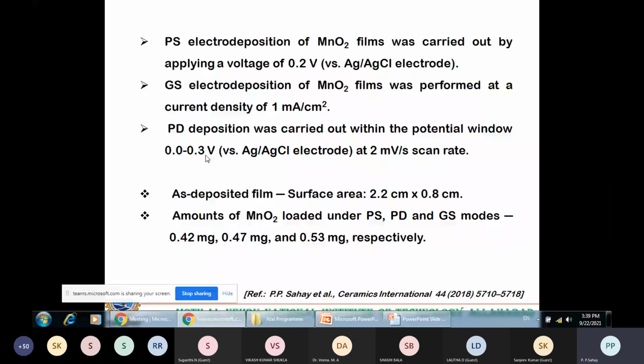This result I published in the Ceramics International journal, where complete details are given. The deposited surface area of the film was 2.2 centimeter by 0.8 centimeter. And the mass of manganese oxide deposited in the potentiostatic, potentiodynamic, and galvanostatic modes was 0.42, 0.47, and 0.53 milligram respectively.